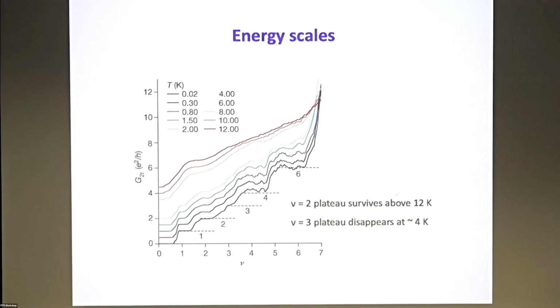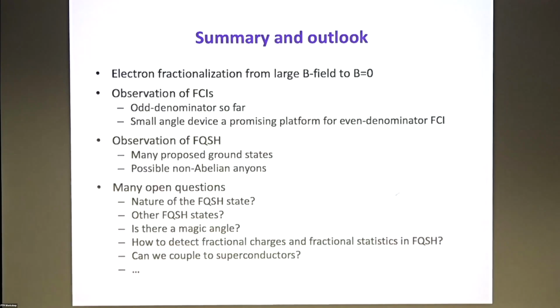And finally, the energy scale of the states. We can do temperature dependence. The short message is that the nu equals 3 state disappears at a temperature of about 4 Kelvin, so that's roughly the gap size of the state. So it's a pretty small energy scale. And with this, I just put down the summary and I'm happy to answer any questions.